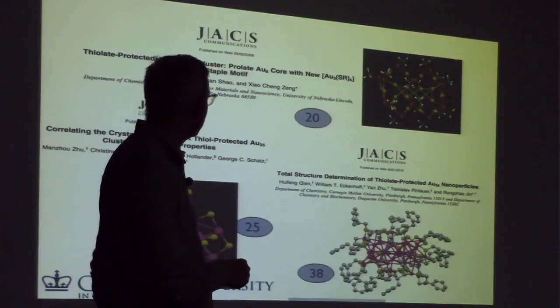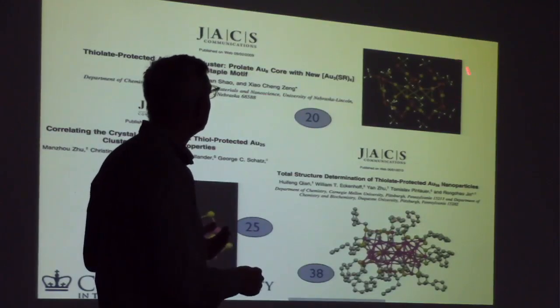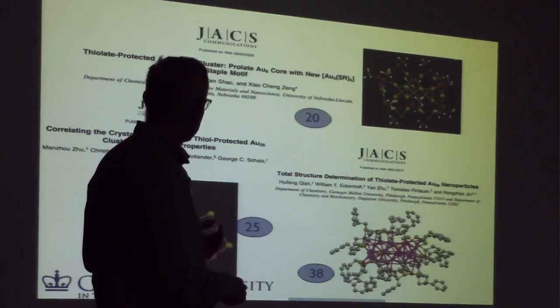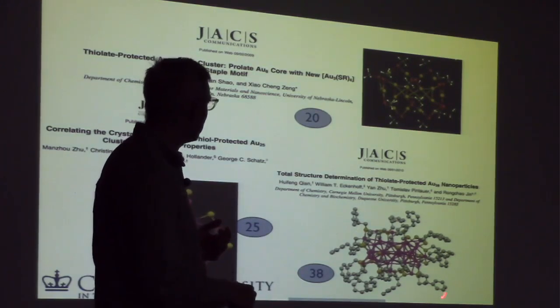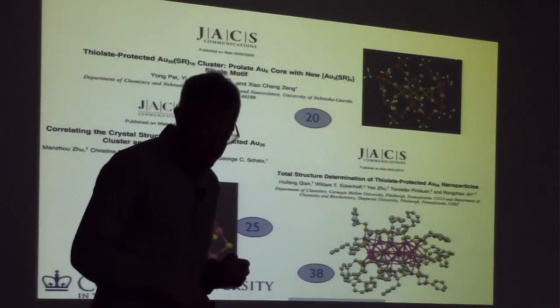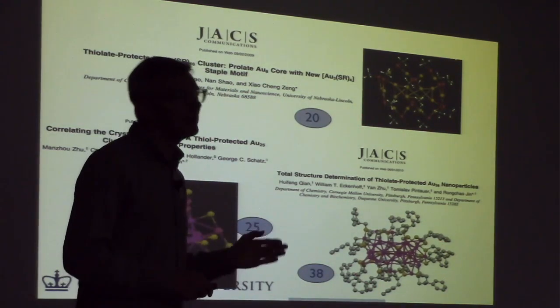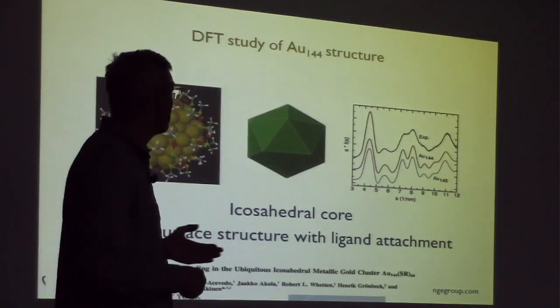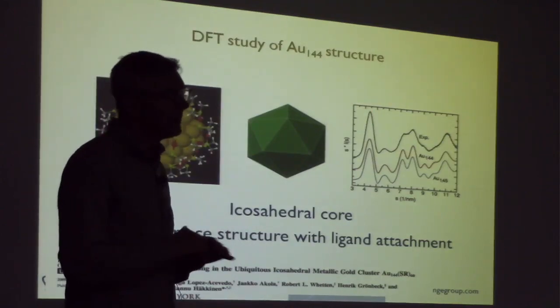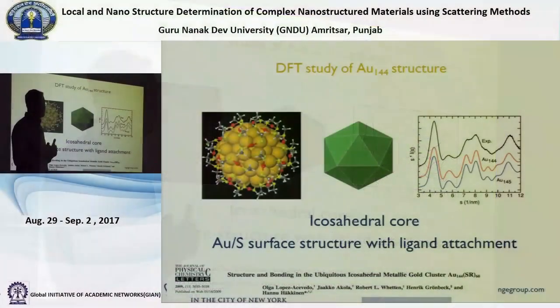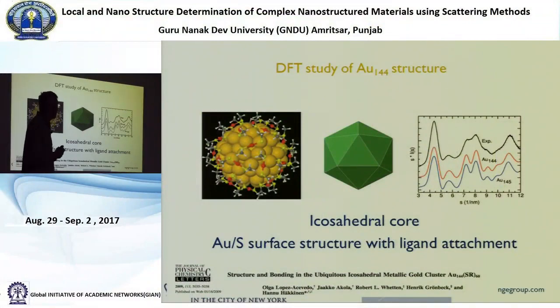I said, okay, we'll run our DFT program, we'll predict the structure, and this was their prediction. For the 20, this was a prediction for the 25, the prediction for the 38. Now, one of the most famous gold clusters of all is gold 144. This is a very, very stable cluster of gold. It has 144 gold atoms in it. And it's so stable that you can actually make powders of it, but very small amounts, like micrograms of powder. But it's like this black powder.